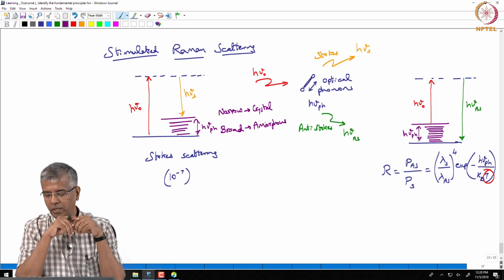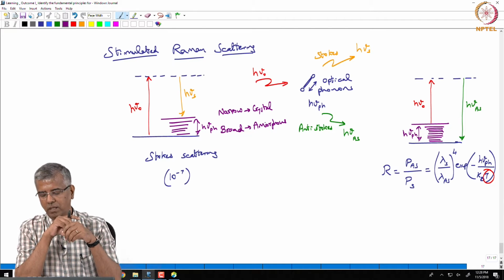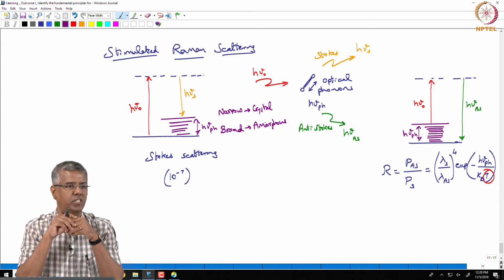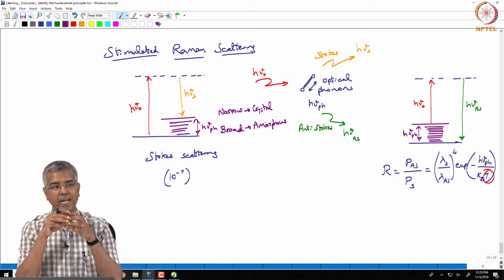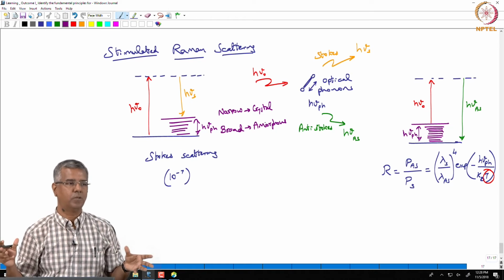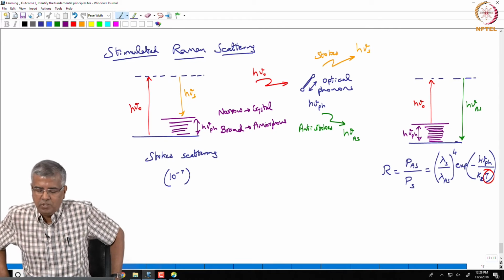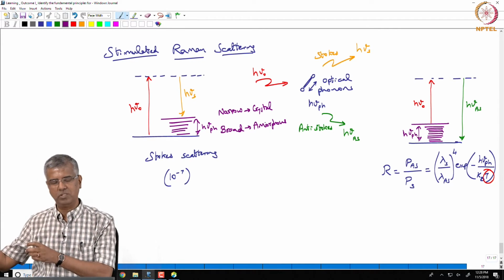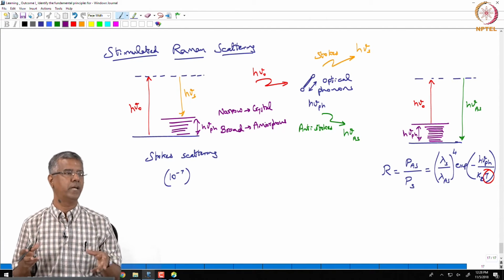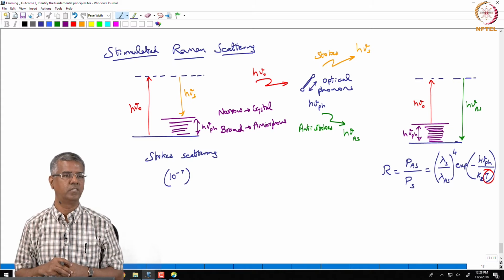And you can also imagine that I am showing one particular molecule for which the phonon energy will have one particular structure. In reality that material may have multiple molecules, different types of molecules. Like even in a germanosilicate fiber, you have germanium oxygen bonds, you have silicon oxygen bonds, right. Each of those bonds exhibit a different phonon energy spectrum. They have a characteristic vibrational mode with each of them.